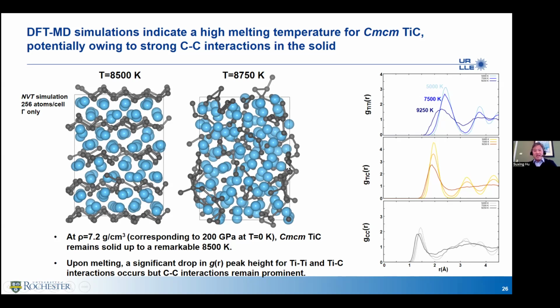Another surprise she found is that even when the system is melted, for example, the right panel showing you here at 8,750 Kelvin, you can still see the carbons. They have not totally become fluid yet. They become a chain, right? If you take a look at the rightmost panel, it shows you the g(r), which is a pair correlation function. And you see the titanium correlation function at over 9,000 Kelvin looks pretty much like a fluid, because the curve just fills up. And this simply means titanium becomes a liquid.